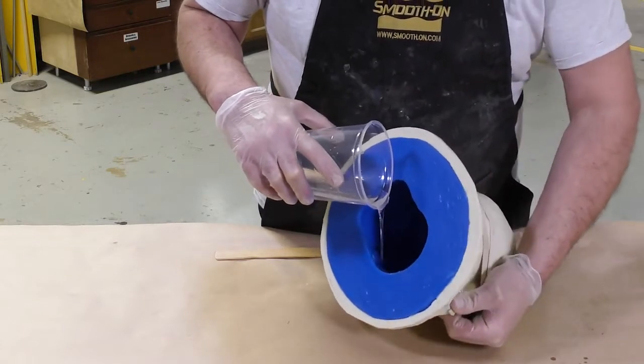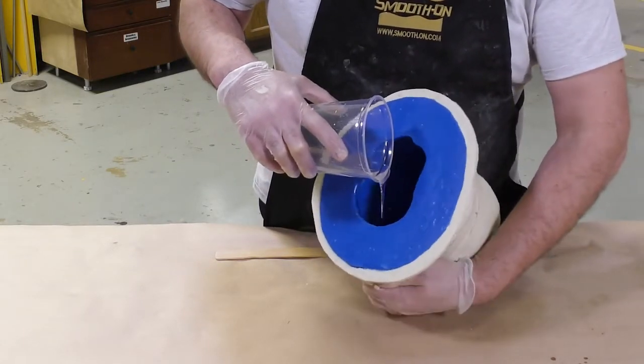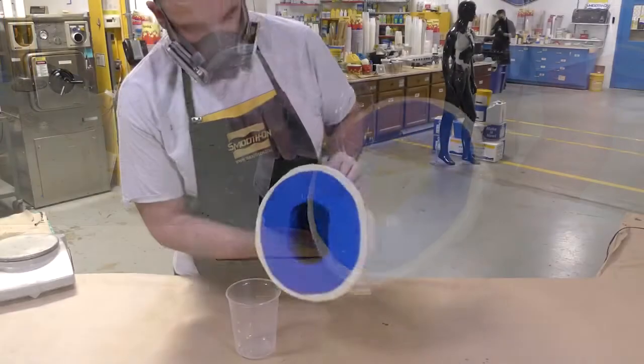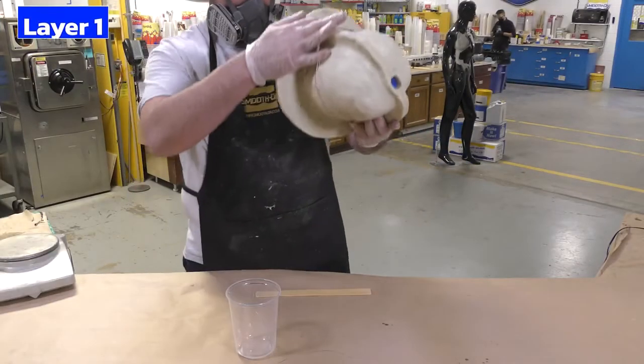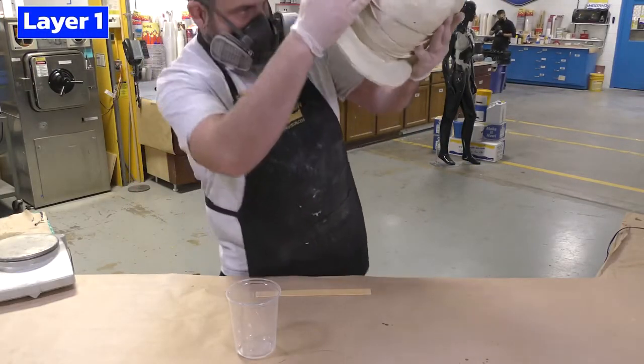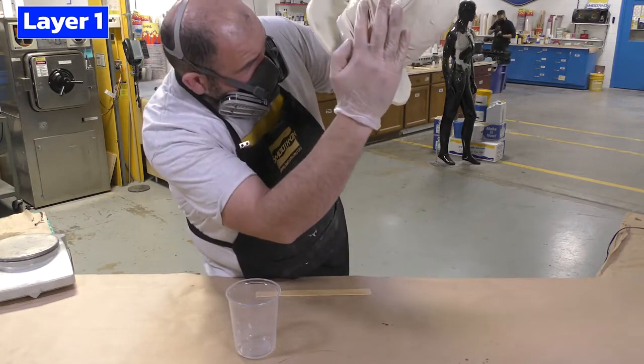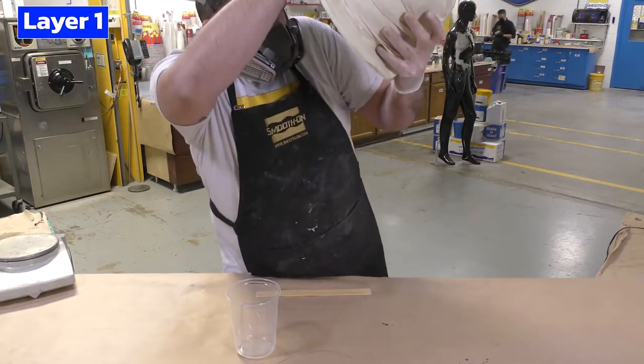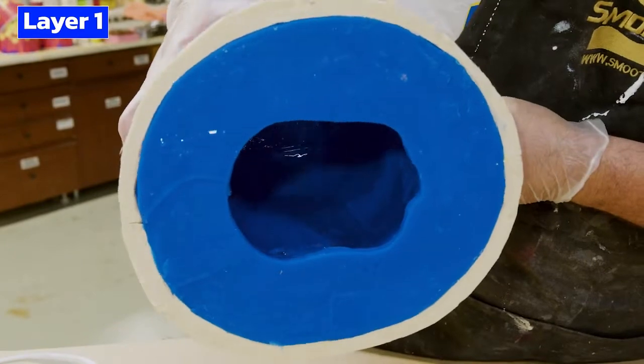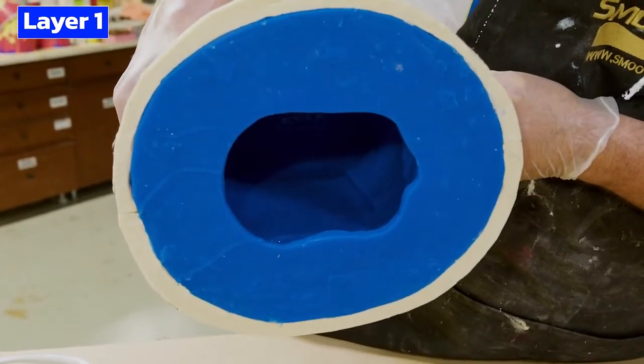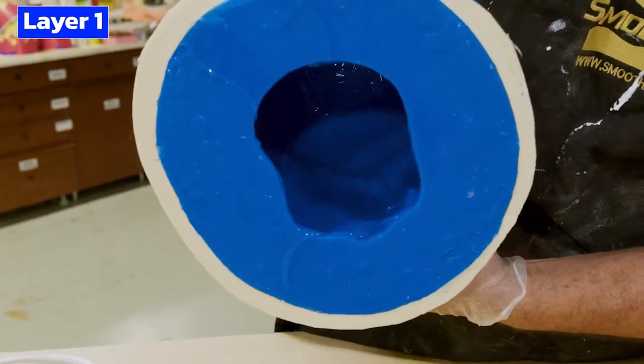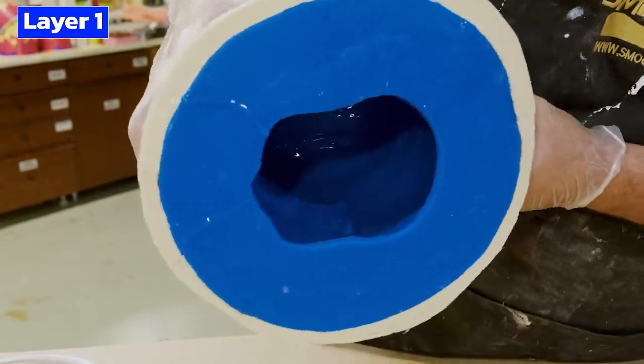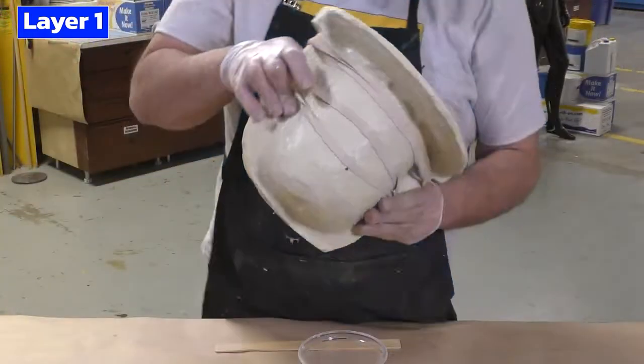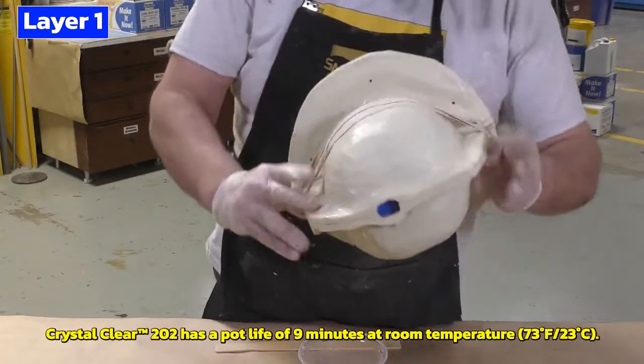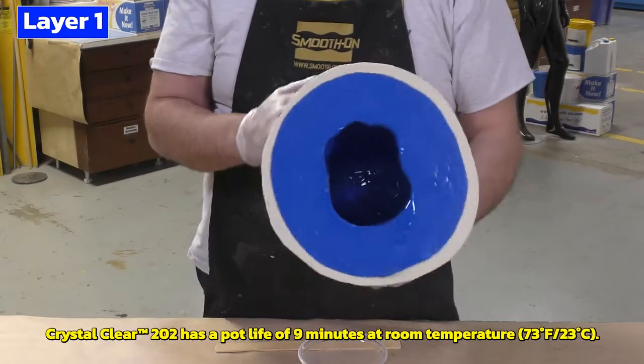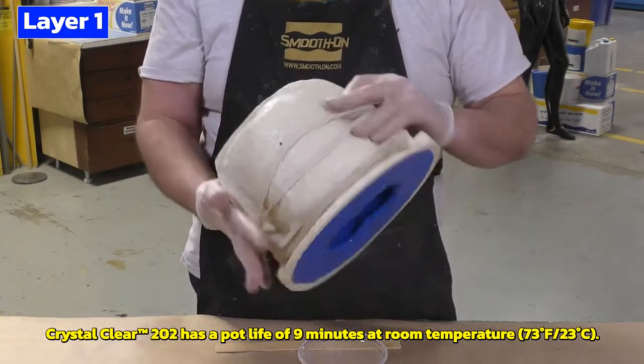And then while looking inside the mold, which we have the benefit of doing because it has a large opening, we can check and make sure that the resin that we're using is coating the entire inside so that all surfaces have a coating of the crystal clear. After that, we're going to spin the mold in a 360 degree way to make sure that the resin is coating the entire inside. And we're going to continue doing that until the material has set up.